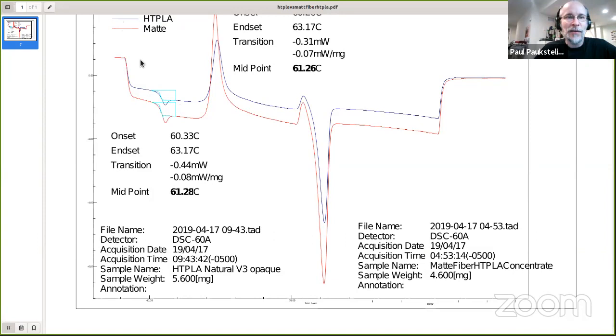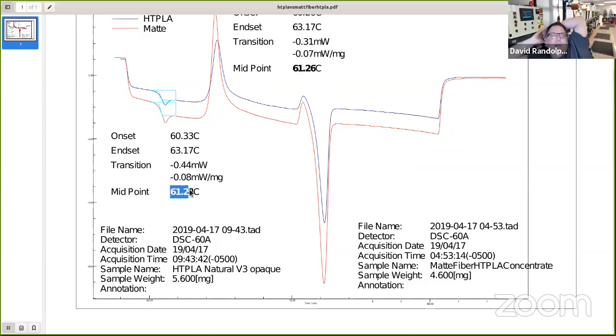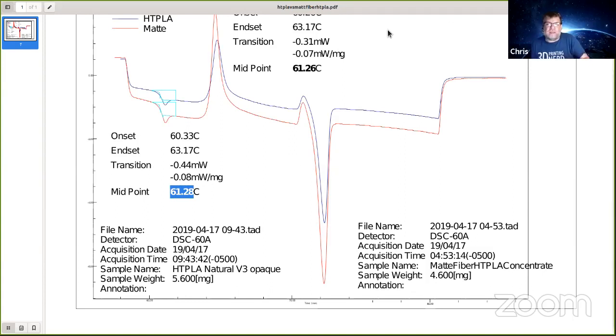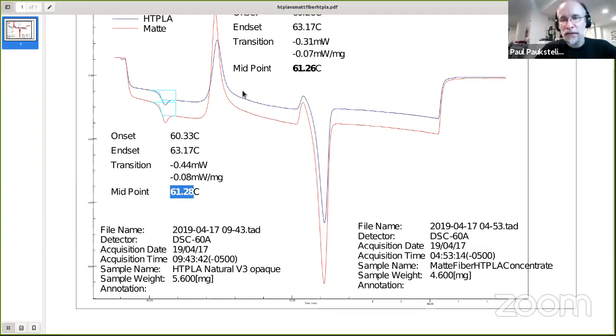So the HTPLA is the blue line here, the matte fiber HTPLA is here, and these are the glass transition temperatures, 61.26 right, and 61.28. So adding the matte fiber did not change glass transition temperature for this. This is neat to see this example, Paul, because we can see the difference from the last one without the little extra dip at the end. Yeah. So right. So you always have this. This is your glass transition temperature. This is the cold crystallization that you have whenever you have HTPLA.